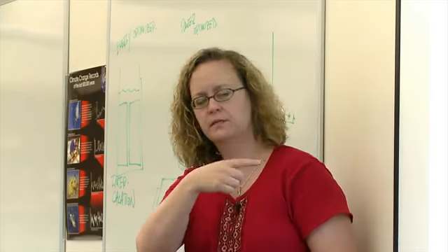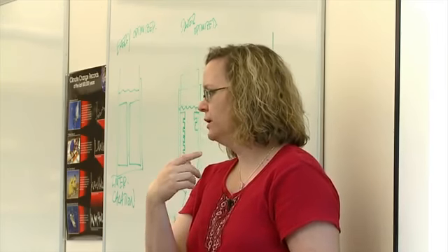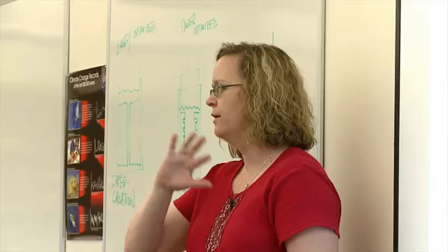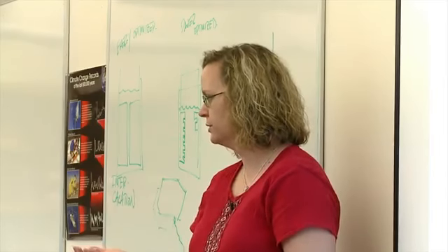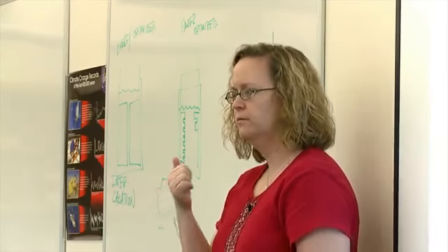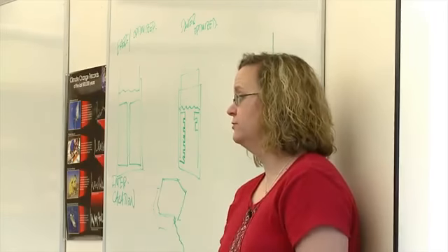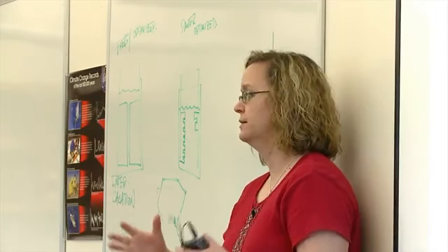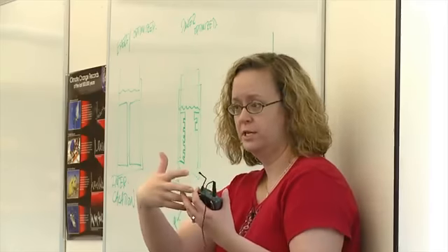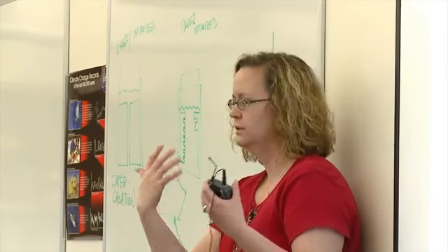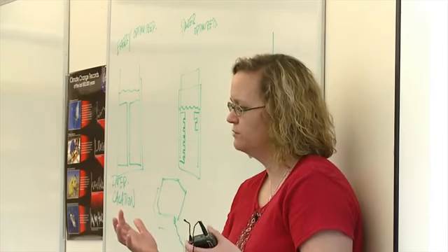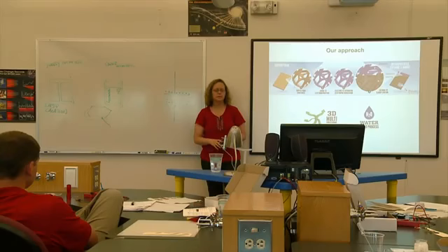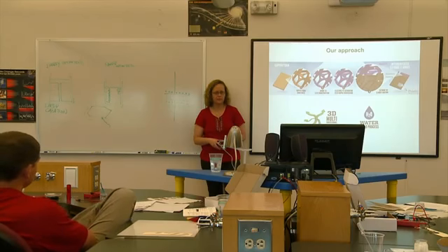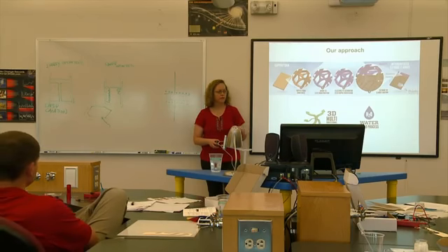We can't really have that because of our architecture. So we had to come up with a way to conformally coat every nook and cranny with this polymer electrolyte. It has to be mechanically stable, but it also has to be mechanically flexible, because remember I told you the electrodes expand and contract, and now ours are interdigitated, so they have to expand and contract in concert with each other, and the polymer has to be flexible enough to accommodate that. It has to be stable at high temperature, because batteries get hot, especially if you charge or discharge them really fast. It has to let lithium ions go through, but it can't let electrons go through at high voltages.